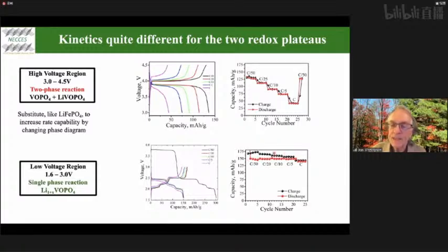In the black is the charging capacity, and you can see that the charging capacity is quite a lot higher if we're at the slower rate. So we're getting serious side reactions occurring here. And this should be no surprise because vanadium phosphate is used as an oxidation catalyst. So we'd expect it to react.